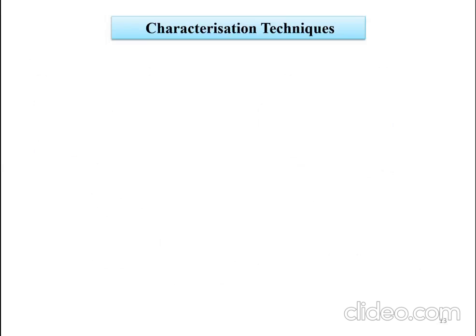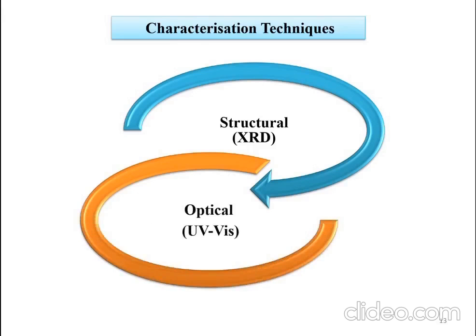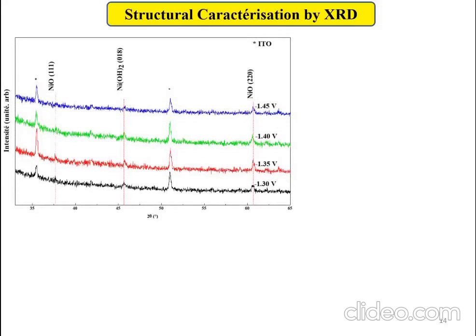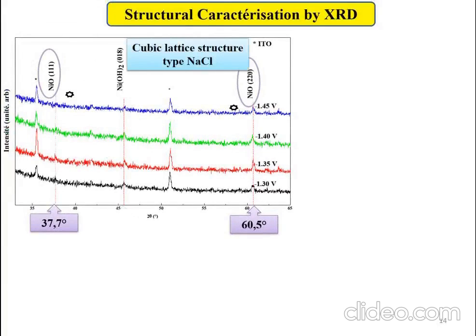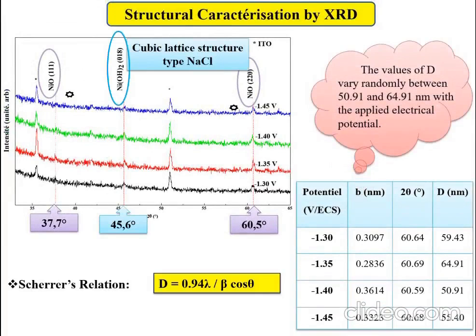Characterization. The second part presents the characterization techniques that we used. Structural characterization by X-ray diffraction was presented to show the crystallographic parameters for the cubic structure of nickel oxide. The values of the diameters vary randomly between 50.91 and 64.91 nanometers with the applied electrical potential.